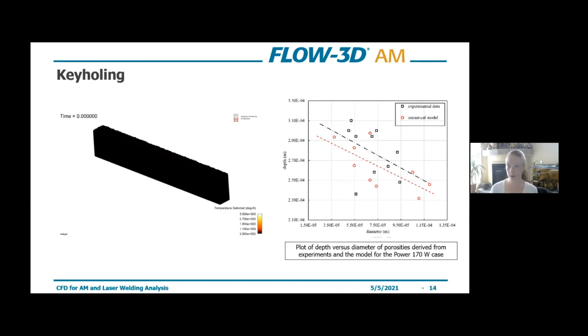What's notable of this study is that these researchers compared both the depth of the resultant pores as well as the diameter between the simulations and the experiment. If you look here on the graph on the right-hand side, the data in black is the experimental data, and in red is the numerical data. We can see very good agreement in terms of where those pores are with respect to the depth of the part, as well as the size of them. Good agreement between the numerical model and the experiment.